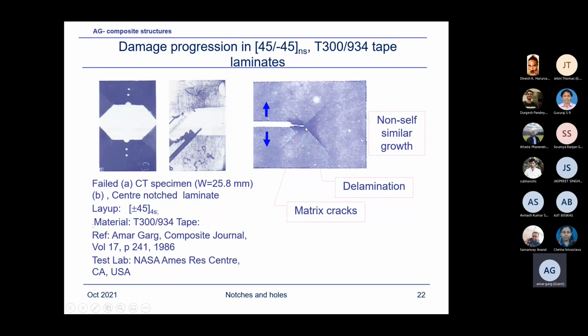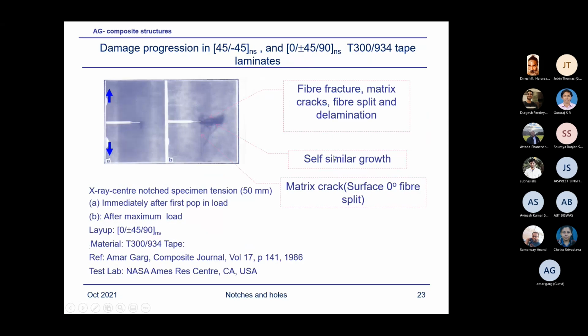Now, if it is a metal, you would find the crack will propagate along the same plane as the initial crack, in the same direction. But in the composite, the damage doesn't propagate in the same direction, unless it's a unidirectional coupon and you're loading at 90 degrees. Then the crack will be like a delamination. Otherwise, you would never find self-similar growth. We call it self-similar if it's propagating in the same direction. If it's not, it is non-self-similar. So this is non-self-similar. Similarly, this is a quasi-isotropic laminate. As you can see, at smaller loads the damage is starting, and near the fracture much larger damage has occurred. So this we can virtually call a self-similar crack growth. The crack is growing, although there's a lot of damage away from the crack plane.